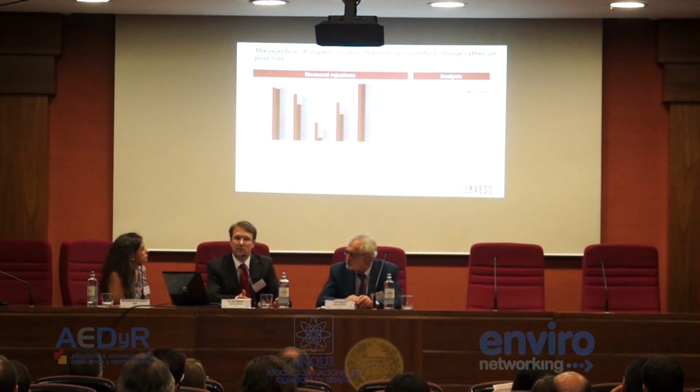The last experiments Lean did were actually to show the rejection of organics. While on the salt side you can always discuss the electrostatic interaction, on the organics this effect is of course much lower. So they tested isopropyl alcohol with our low energy membranes and the competitive benchmark, DMF, urea, ethylene glycol, and glucose. With isopropyl alcohol and glucose, all the membranes had almost the same rejection. We could show that at least with DMF, urea, and ethylene glycol, we have a higher one.